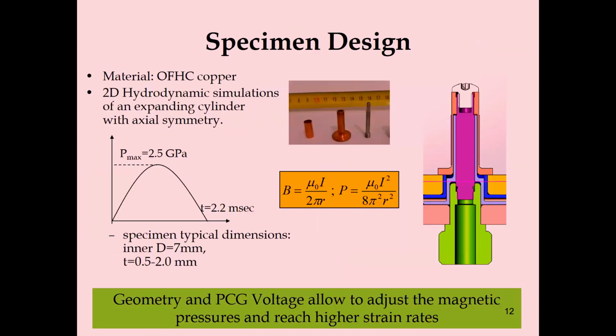We're using interferometry to look at the velocity of the expanding cylinder under the dynamic loading. So we could design different specimens. We could characterize the magnetic field and then the magnetic pressure, and we could see characteristic sizes here. We have an inner diameter of 7 millimeters, and the wall thickness is between half a millimeter up to 2 millimeters. And we could vary the geometry and the voltage to adjust the magnetic pressures and reach higher strain rates.